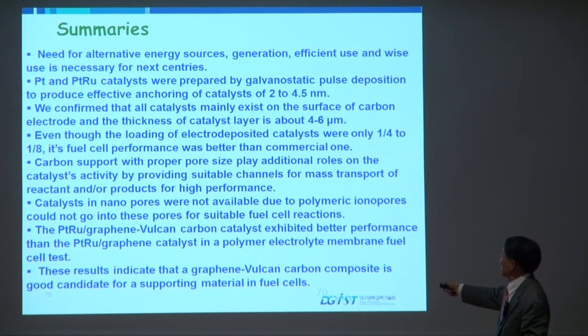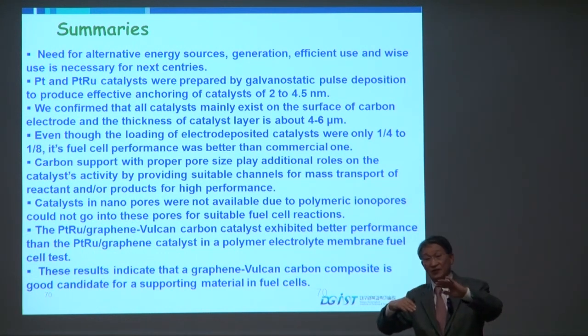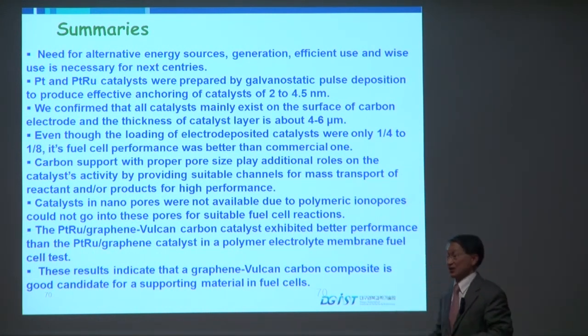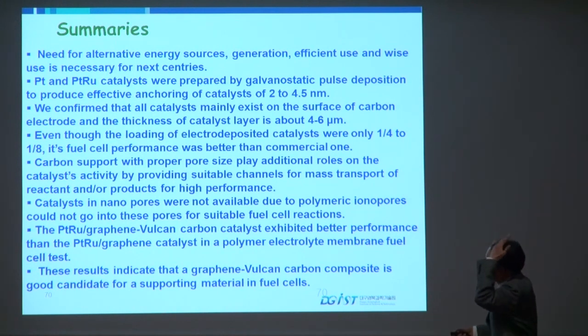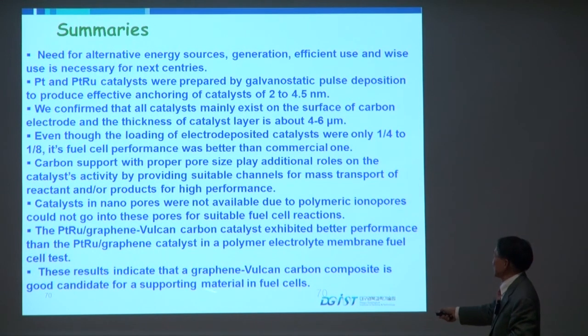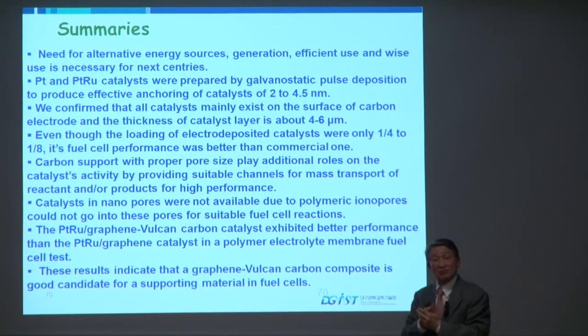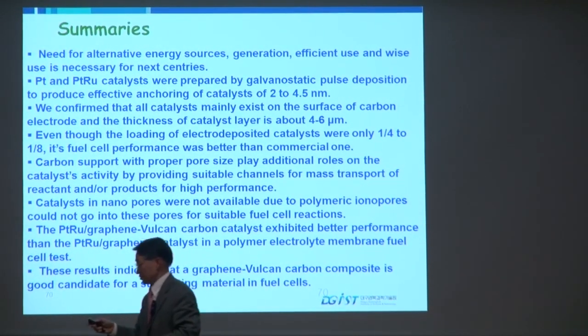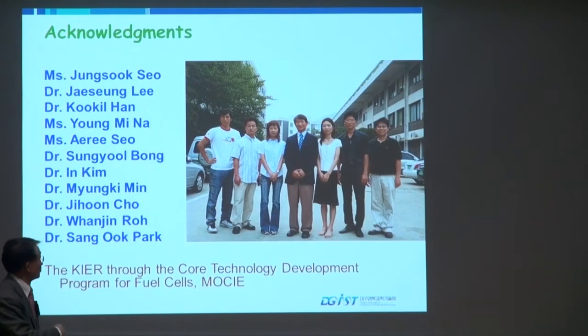And nanopores were not available due to polymeric ionomers. They could not go into these pores for suitable fuel cell application. That's the comparison of aqueous media and the solid electrolyte media. And the platinum ruthenium graphene Vulcan carbon catalyst has better performance than this. And this composite can be utilized for future supporting materials.